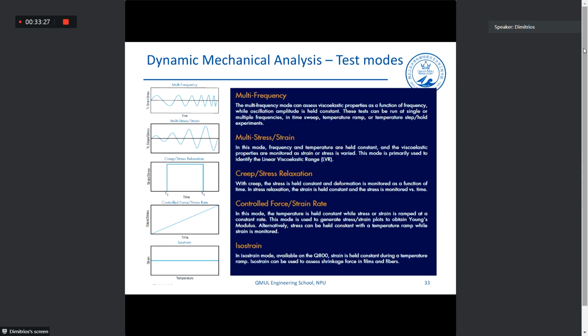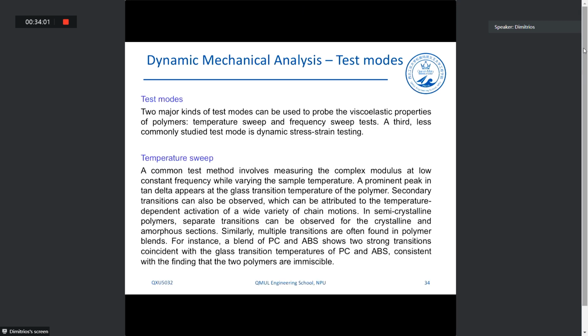Yeah, so in terms of its standard use, its basic operation of DMA, we apply sinusoidal varying stress, and we measure the deformation. The stress is usually applied at a constant frequency, but we can also do a multi-frequency test. In this case, we assess the properties as a function of frequency, while the oscillation amplitude is held constant. Anyway, these are not too important for you. The two, as I told you, the two main test modes are temperature sweep and frequency sweep test. Temperature sweep is the most common.